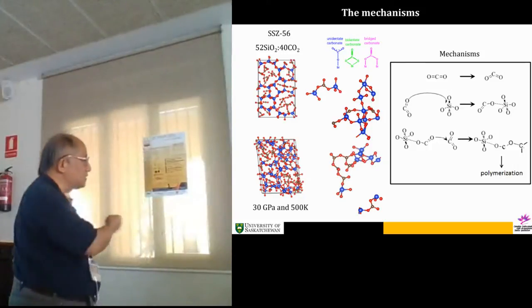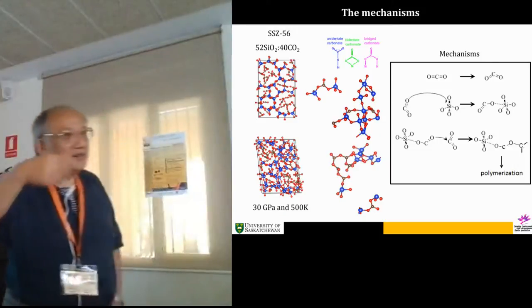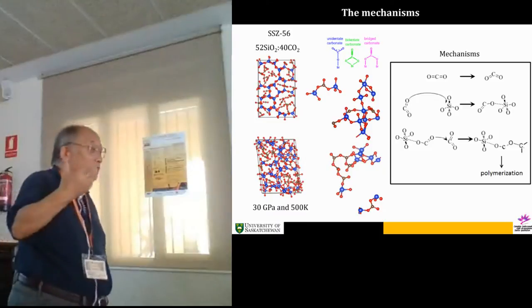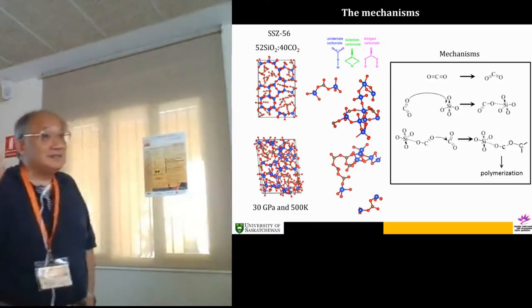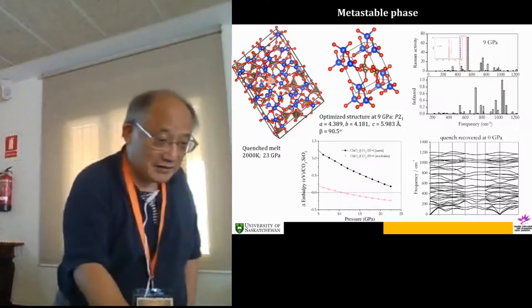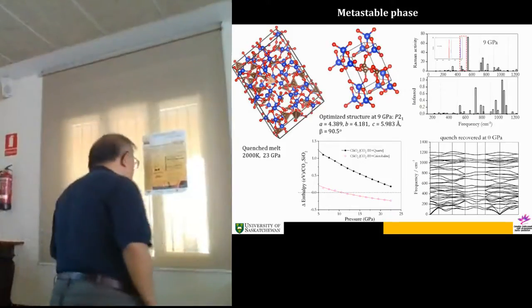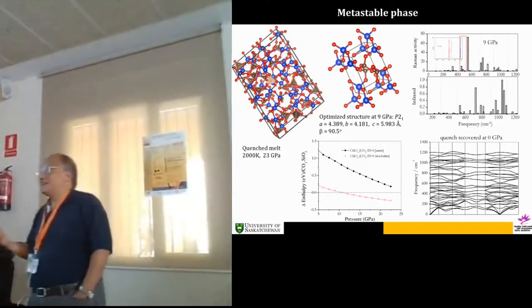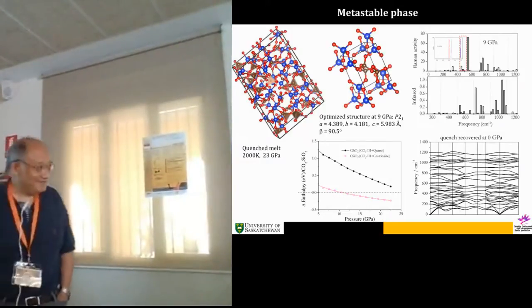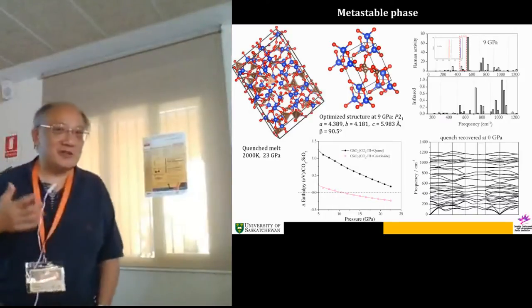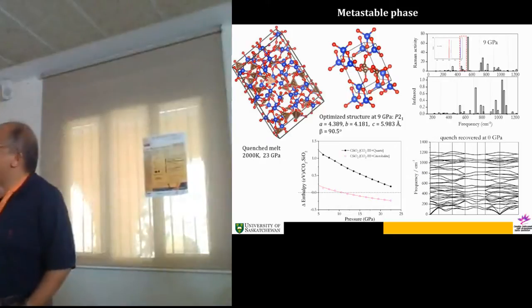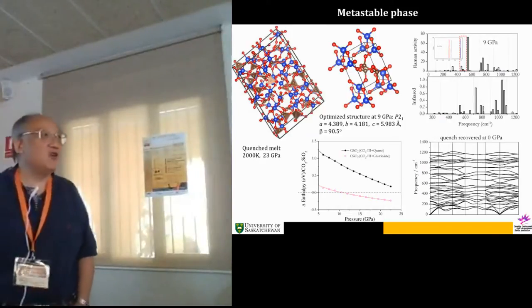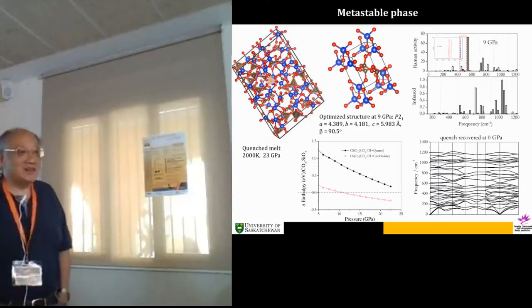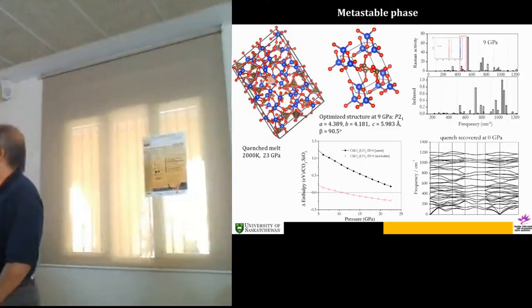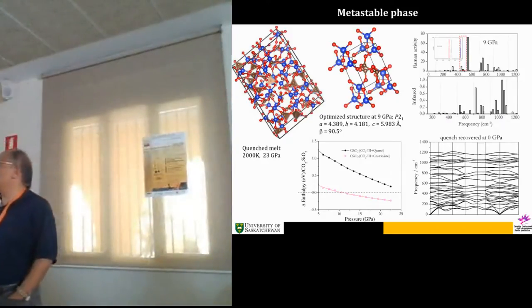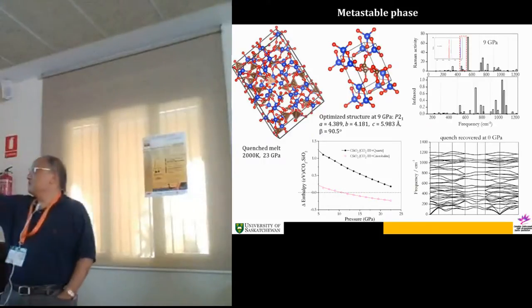And then you can now start to think, how about other systems? All right, without doing experiment or without doing calculations. And that's what theory is supposed to do, it is predictive, right? That's what theory should be, all right? So how about this metastable crystal-like state? Initially, I don't believe it exists. So I take the structure and cool it. Now, you never would expect a cooled structure will give you a crystalline product. But you can see the incipient formation of the tetrahedron of the CO4 interacting with SiO4. So at that time, we say, well, I will never get the crystalline structure. You just construct a structure, a model of SiO4 and CO4.